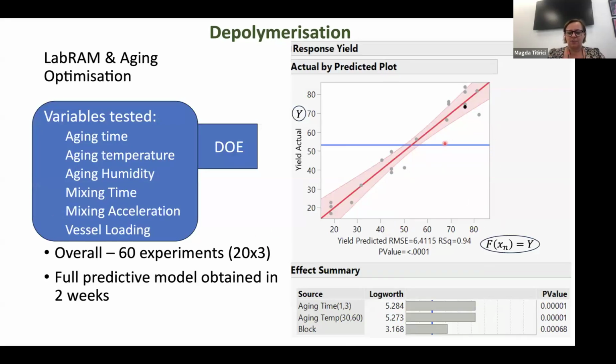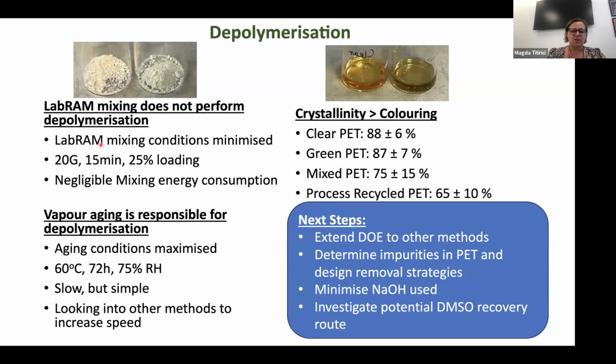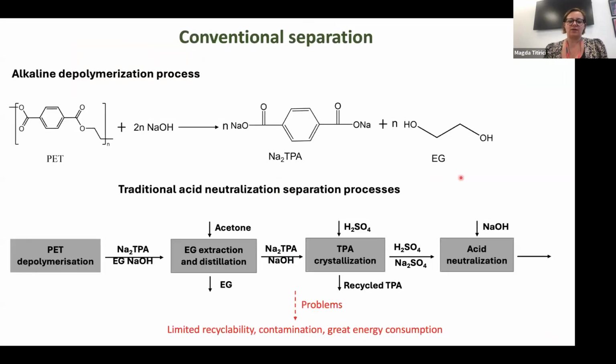And this is our design of experiments. What we've learned from this is that we have the best aging conditions maximized, which is 60 degrees, 72 hours. But this is still a bit slow, though it's simple. So we're looking at other methods to improve the speed. We're also looking at different PETs, some clear PET that we get from Starbucks cups on the campus, green PET that we get from San Pellegrino bottles, and some mixed PET that we get from a real plastic recycling company. So we still have a lot to do to optimize the depolymerization.